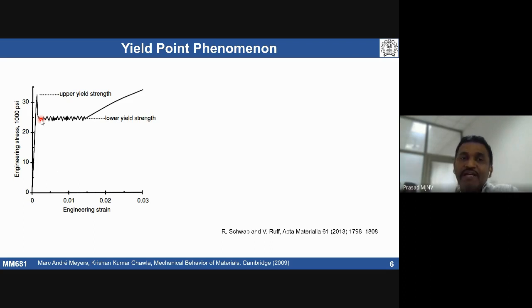What does unstable plastic deformation mean? Solutes have their own interaction. Solutes already within a grain may have some velocity because of diffusion taking place due to temperature and strain rate. But the dislocation is also moving freely, very fast. So that can lead to a kind of unstable plastic deformation. This elongation is called yield point elongation.